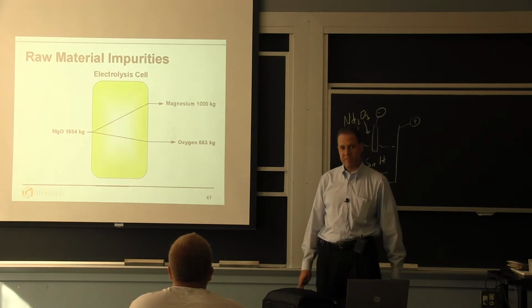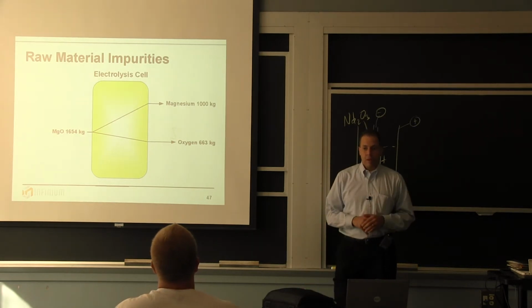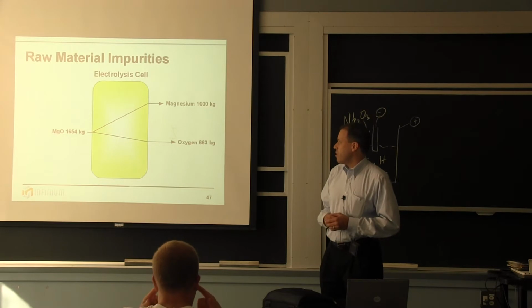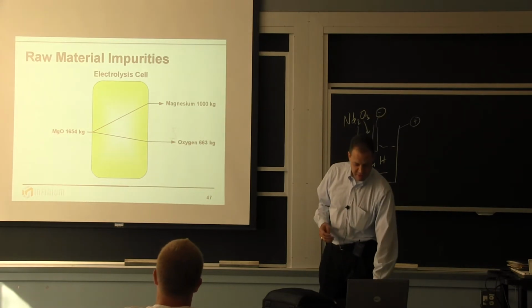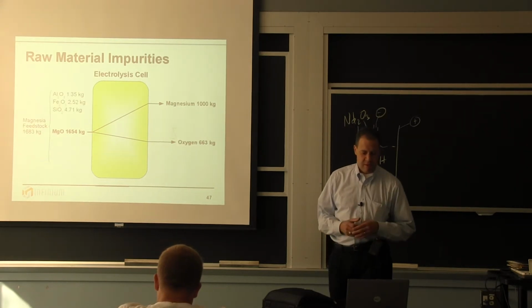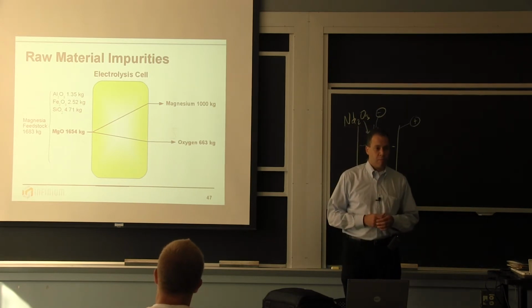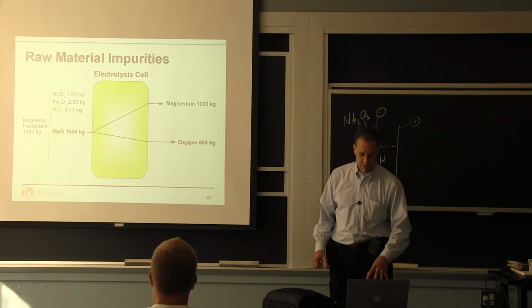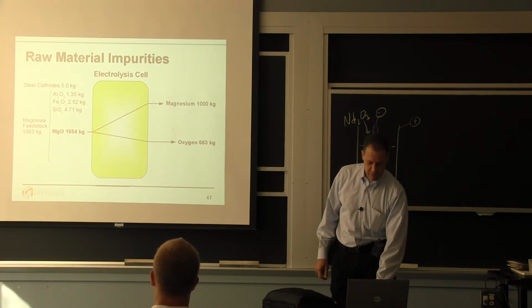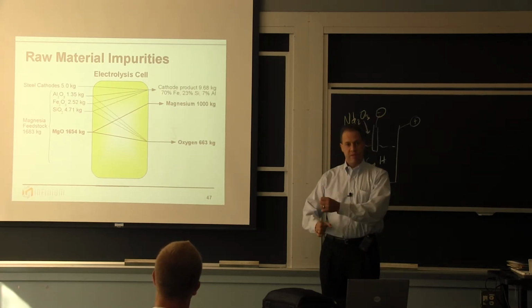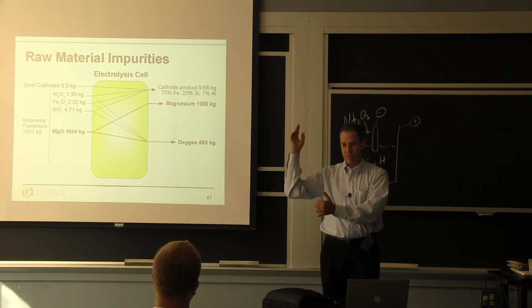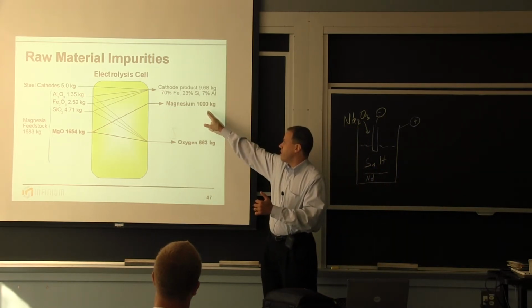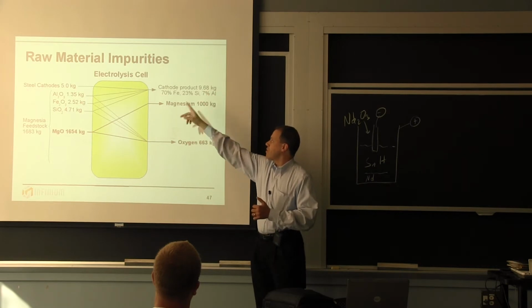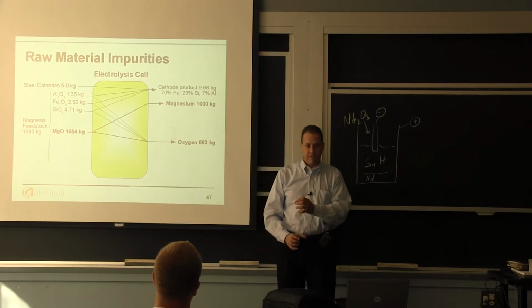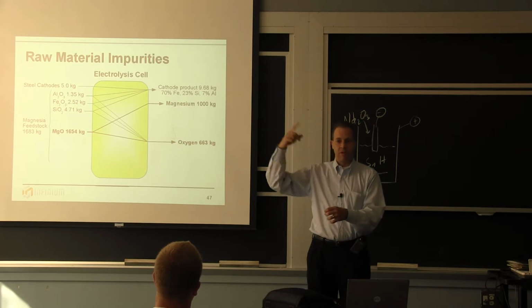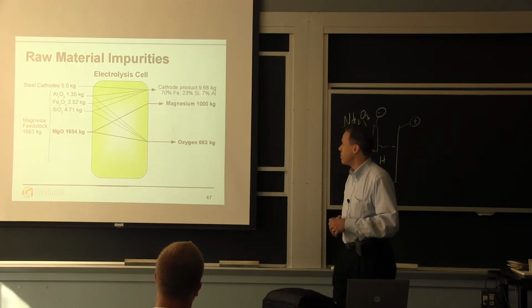So just in terms of what happens to the impurities, the basic reaction is magnesium oxide to magnesium plus oxygen. But the feedstock has a lot of impurities, particularly more electronegative metals like aluminum, iron, silicon, or rather their oxides. Those plate out on the steel cathodes. For every metric ton of magnesium we produce, we get about 5 kilograms of these impurities plating out on the cathodes. So we have to replace those every so often.